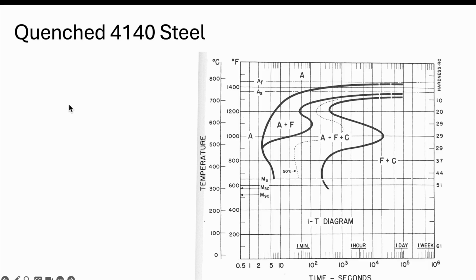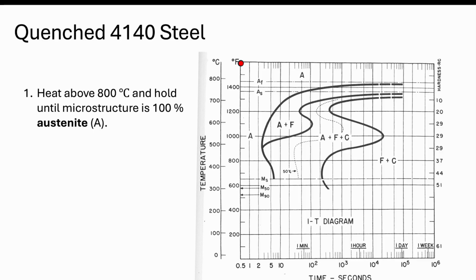So I want to start with what we would call the quenched. When we talk about quenched, we're talking about a rapid cooling. With all of these transformations that we're going to do, we have to start with austenite. So I drew a dot up here at the top. This means that for any of these reactions with isothermal transformations, we have to start with 100% austenite. In this case, I'm going to go above 800. In our lab, we do 850 Celsius, but this can be adjusted a little bit. Anywhere above this austenite finish temperature, we would have 100% austenite. So you typically hold for a certain amount of time to make sure that we have 100%. So that's the start. We're assuming that we start these reactions with austenite.